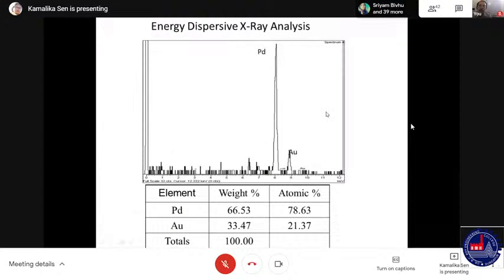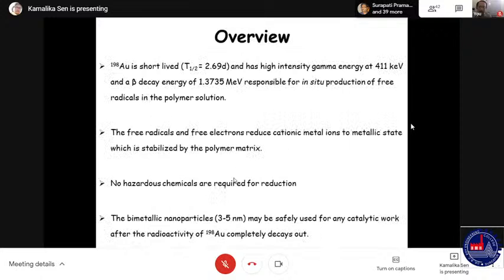This is the closer view, and the energy dispersive X-ray analysis says that there is a higher percentage of palladium in the mixture than gold. And the overview is that without the presence of any kind of hazardous chemicals, only with the radiation in the solvent, it can generate the nanoparticle. This thing also is not possible with external gamma radiation. Only in situ gamma dose is responsible for the bimetallic.